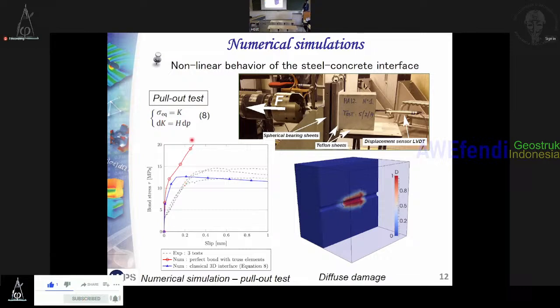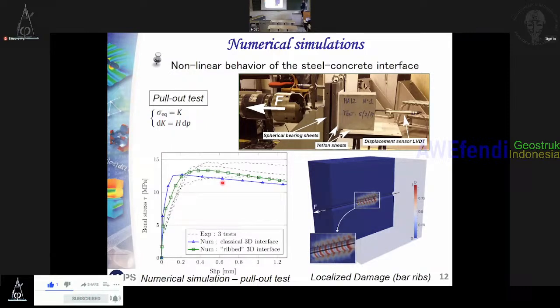And here, for instance, if you suppose that you have perfect bonding, you can see that it's not working. You may have access to the beginning of the curve, but not the end. And if you use only one parameter, it's not possible to completely predict the shape of this curve. Of course, if you add one or two parameters, it will be better, because the more parameters you have, the more you will fit. I completely agree with you.